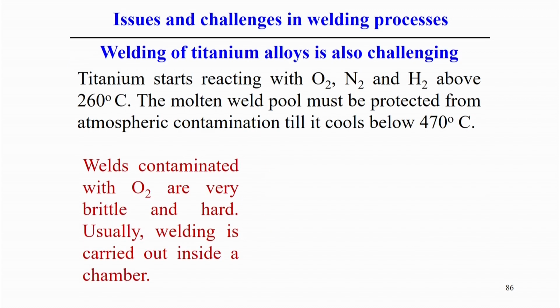Another issue of the welding process is the welding of titanium alloy. Welding titanium alloy using the normal arc welding process is really very challenging, because at high temperature titanium always reacts with oxygen, nitrogen and hydrogen, and the molten weld pool must be protected from this atmospheric contamination until it cools down to a certain temperature. So that is a real problem.